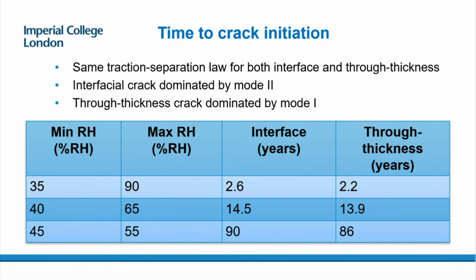And these are some of our predictions. I have three scenarios here for relative humidity. This varies from 35 to 90 maximum, and this is what you would get on a calm day. And it would take just about 2 years for cracks to start growing. These two are much tighter controls that you would typically have. This is the V&A museum control. And you can see that as you make this more and more controlled, then it will take longer for cracks to start growing. And what we're doing at the moment is, it's fine to find out when cracks will initiate. What's more important is how fast will these cracks grow, because it could be that they initiate, but then they don't grow very fast. If they grow very fast, that's a lot more serious, and that's what we're doing at the moment.